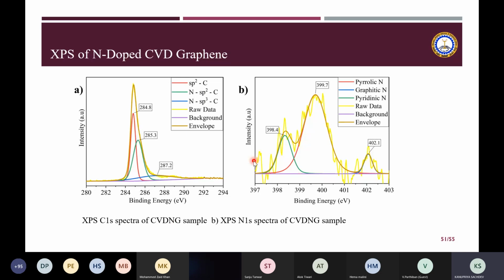When we deconvoluted both these spectra, we could very easily confirm the nitrogen. When you look at this nitrogen spectra, you will see that when the nitrogen in the graphene goes at various, different positions, that gives you either pyrrolic N, graphitic N, or pyridinic N. Deconvoluting this spectra, we could find the presence of all three types of nitrogen. And then we could really explain the modified electrochemical properties of the sample using this.